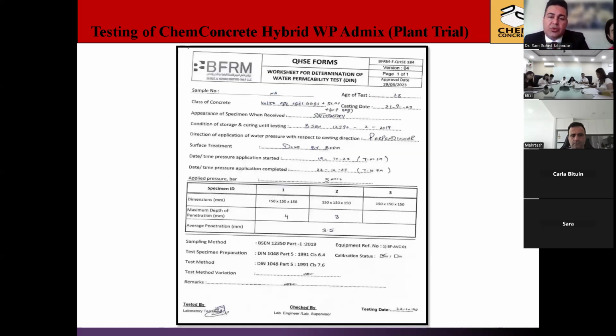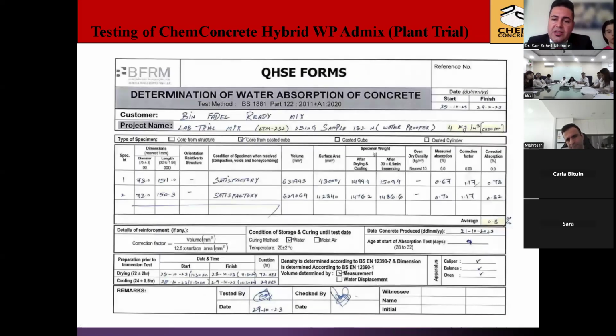And you can see the water penetration depth. The maximum water penetration depth based on the design requirement was, I think, 8 millimeter. But by using only 4 liters, less than half the dosage we recommend, they achieved 3.5 millimeter water penetration, and the water absorption was 0.8%. What's very interesting is that by using less than half the dosage of what we normally recommend, they could pass all their design requirements.